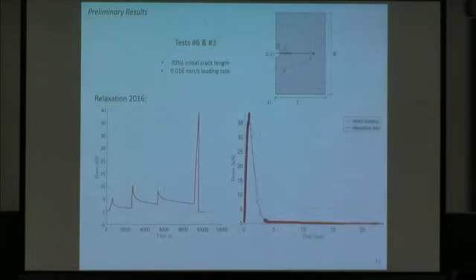So this is a relaxation test we did in 2016, and it's a comparison between test number 6, which is a cyclic relaxation loading, and test number 3, which is direct loading up until failure. So this is how it looks, as I described. We first loaded up, this is time, and then we stopped our engine, which means that our displacement is fixed now. So it starts to decrease a bit, and then we keep loading up until it goes down, and just several cycles, then we load it up until fracture.